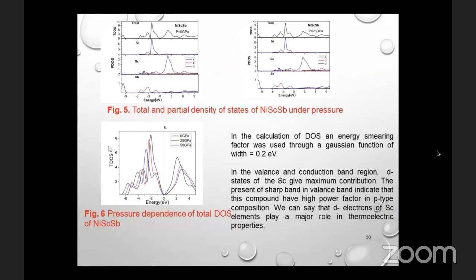And also in figure 6, electronic behavior has been discussed through the DOS for different pressures. It can be seen from this figure that the shape of the curve under pressure has no significant change, showing that the structure of this compound is stable and no structural phase transformation occurs in the investigated pressure.